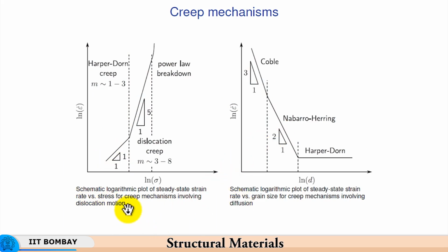So, these are the plots of the different creep mechanisms, and ln sigma versus ln epsilon dot has been plotted. So, you have diffusional creep which has m equal to 1, so it is proportional. Even Harper-Dorn creep, you have m equal to 1 to 3. So, here also it is proportional to sigma, and then you have dislocation creep which is 3 to 8. So, the strain rate increases very rapidly.